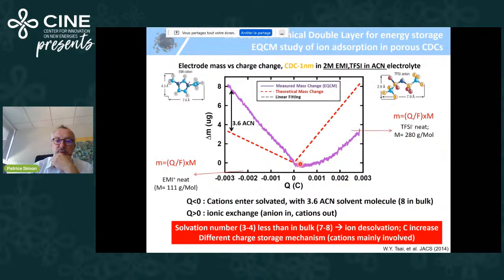Then, when we polarize positively, what do we see? We see something like that. You see, there is a zone here where the experimental slope is less than the theoretical one, which corresponds to the neat TFSI minus. How do you explain that?